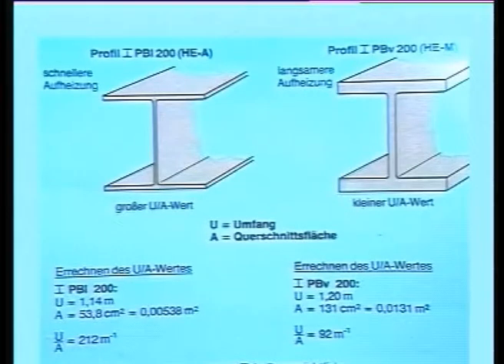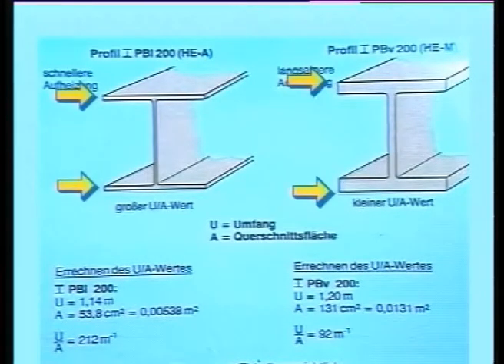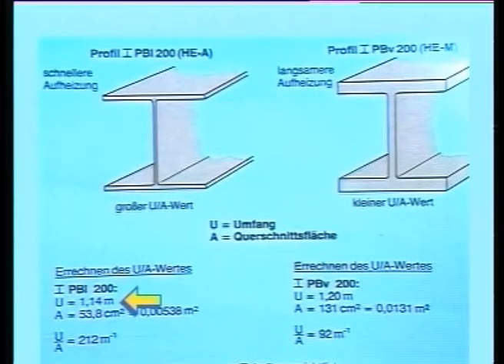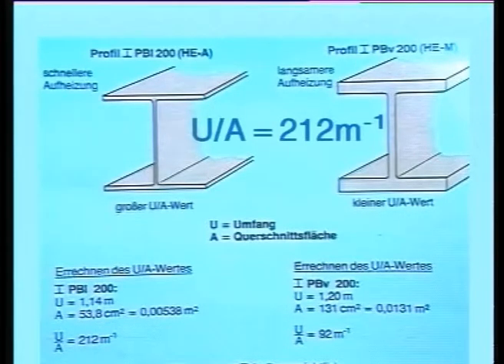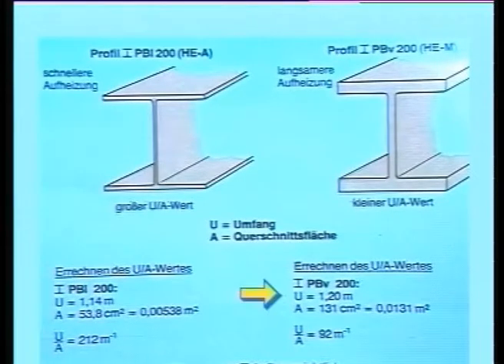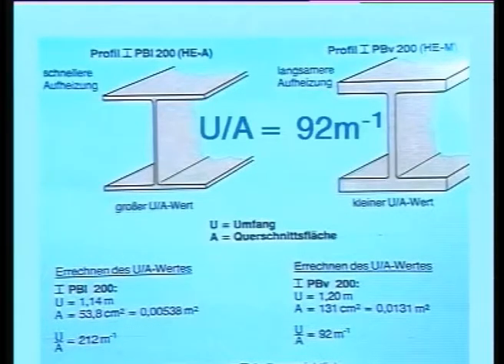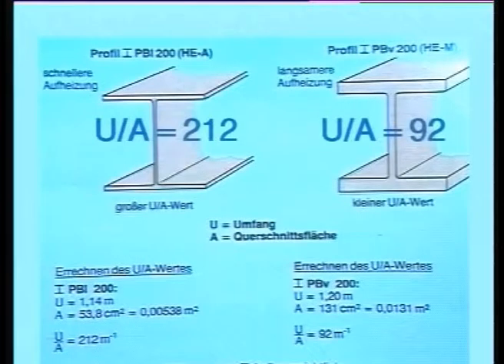We provide a sample computation of two standard steel profiles, IPBL and IPBV, with a nominal height of 200 millimeters. Accordingly, the left profile has a circumference of 1.14 meters and a cross-sectional area of 53.8 square centimeters, resulting in an HP to A ratio of 212 to the power of -1 meters. For the profile shown on the right, we have computed a heated perimeter of 1.2 meters and a cross-sectional area of 131 square centimeters with an HP to A ratio of 92 to the power of -1 meters. The lower HP to A ratio of the right profile is attributable to a higher mass of steel, which results in slower heating in the event of exposure to fire.